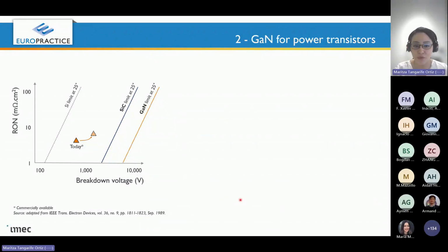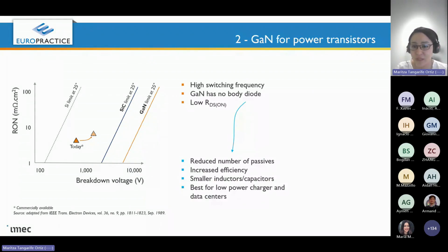There are other factors that contribute to switching losses, and several of them are improved through the use of GaN. One of the loss mechanisms results from the fact that the current in a transistor begins to flow before the drain-source voltage begins to fall. During the time of the fall, and I'm missing the graph here, but probably you're already familiar with it, the losses are very large. So if you increase the speed at which a switch turns on, then you will reduce the losses during this transition. As GaN transistors are able to turn on faster than silicon transistors, they are able to reduce the losses.